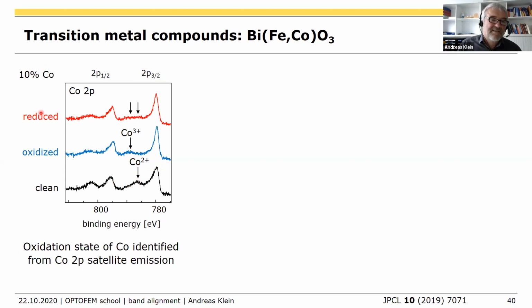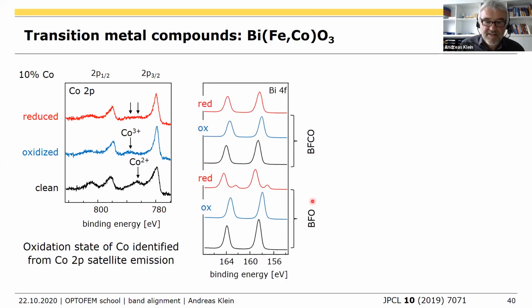And if we reduce the sample, which we do by water adsorption, we get a mixture of cobalt 2+ and cobalt 3+. In principle, you also see the binding energies are changing. But the changes of the binding energy you better see when you look at a bismuth 4f peak. So this is an undoped bismuth ferrite sample, no cobalt. This is the starting condition. This is after oxidation. And this is after reduction.